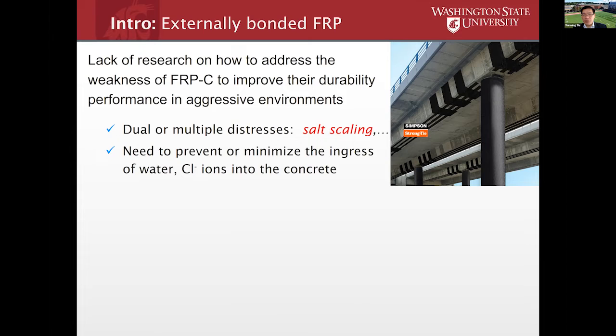However, there's a lack of research on how to address some of the weaknesses of what I consider an FRP concrete composite material, to improve their durability performance in aggressive environments. For instance, the concrete could be subject to dual or even multiple distresses. Like in the case of salt scaling, we're not only looking at freeze-thaw damage, but also chemical attack. There is a need to prevent or minimize the ingress of water. Like we mentioned earlier, if we can keep the water out, we can keep the chlorides out, we can keep the sulfate out, and the concrete will last a longer time.